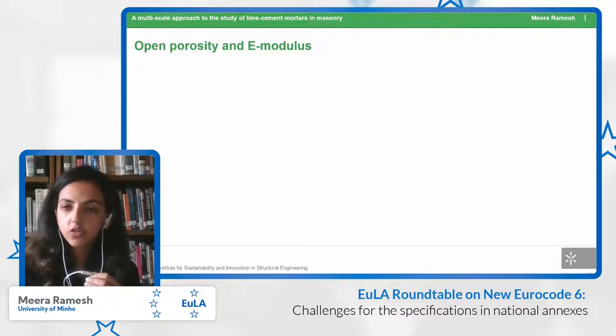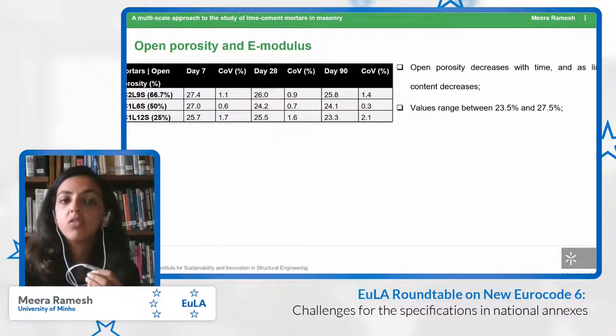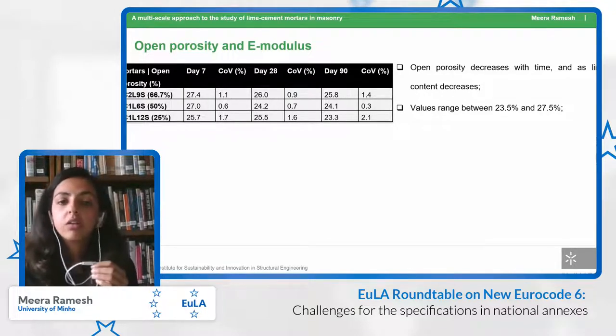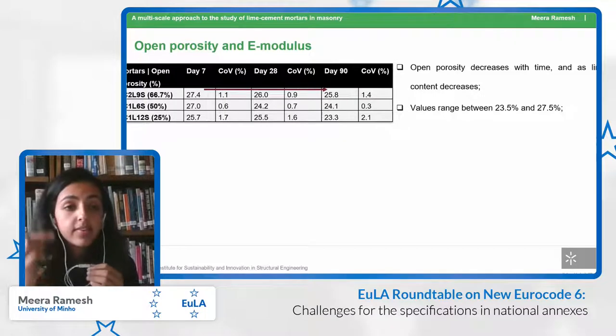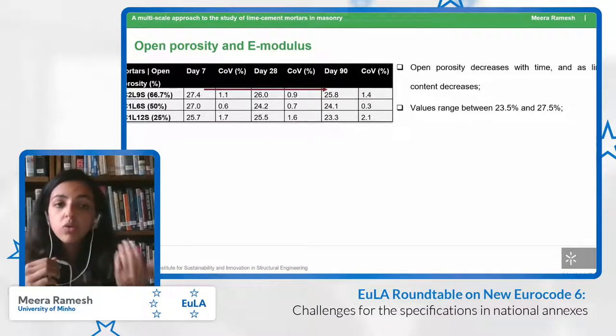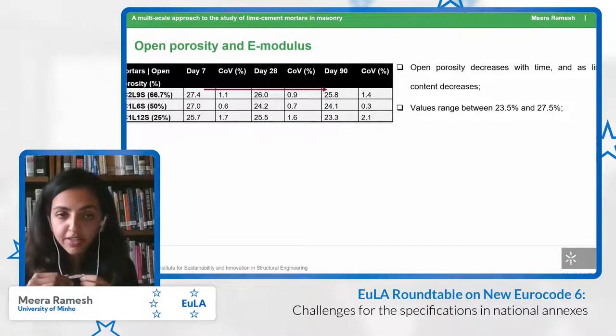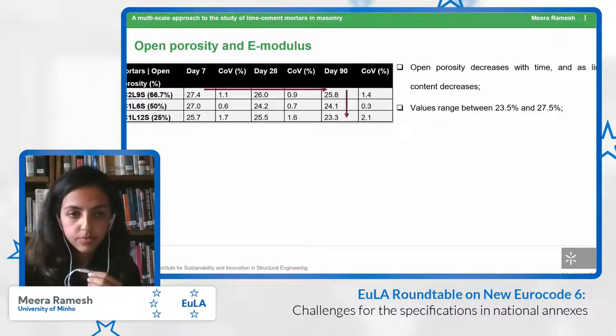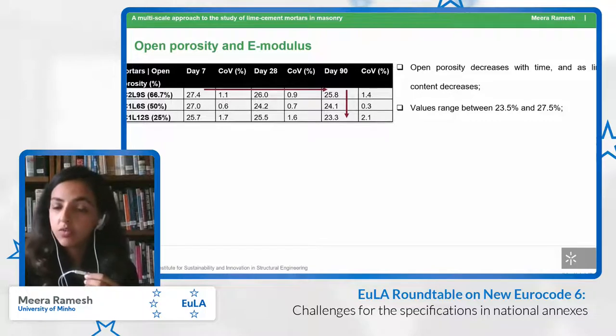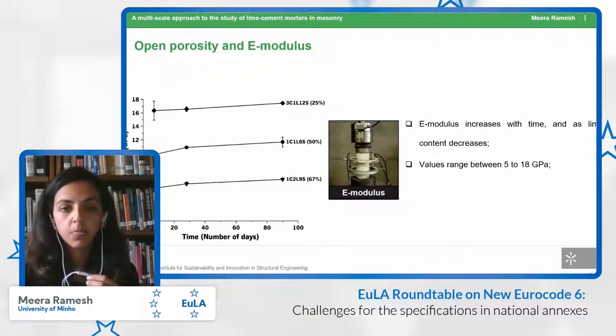Finally, we shortlisted some mixes, 3 mixes in this case, to also study trends in open porosity. And we found that open porosity decreased as the amount of cement in the binder increased, and with time, open porosity reduced as well. The values that we obtained ranged between 23% to 27%.